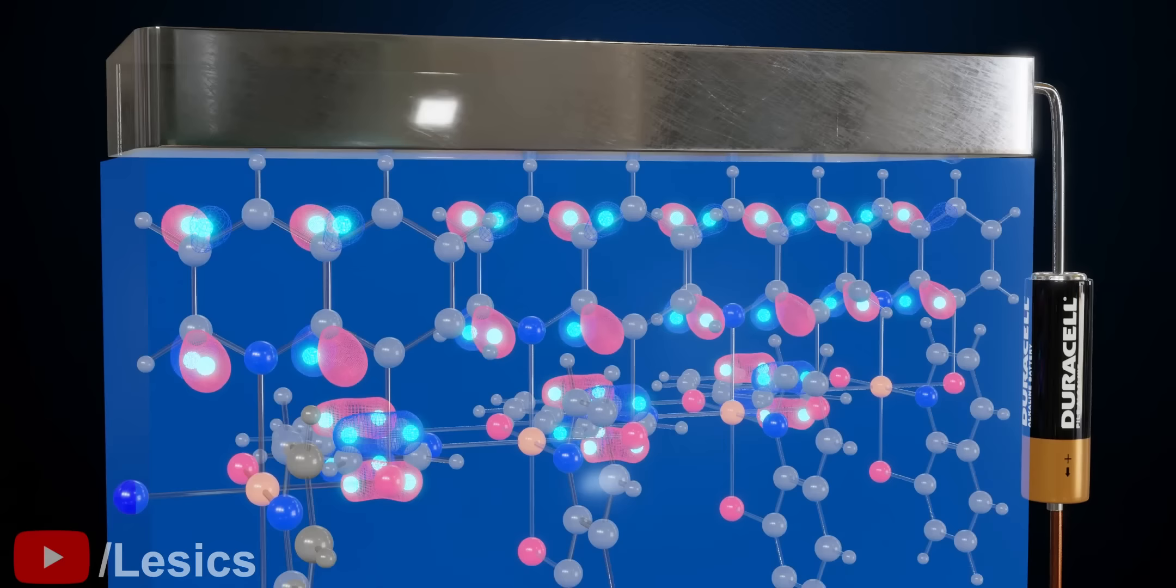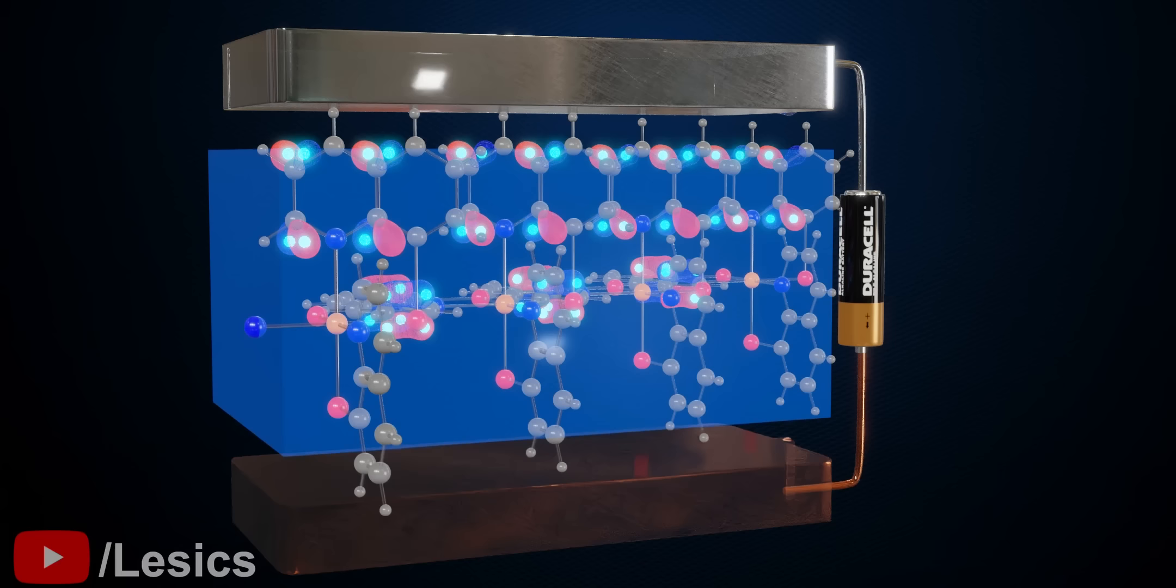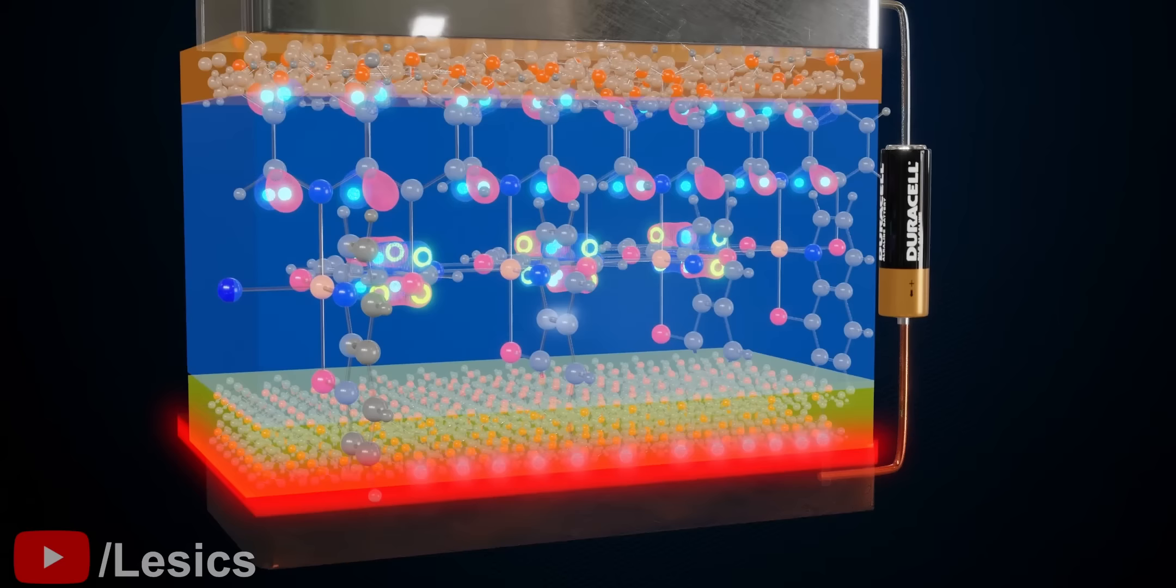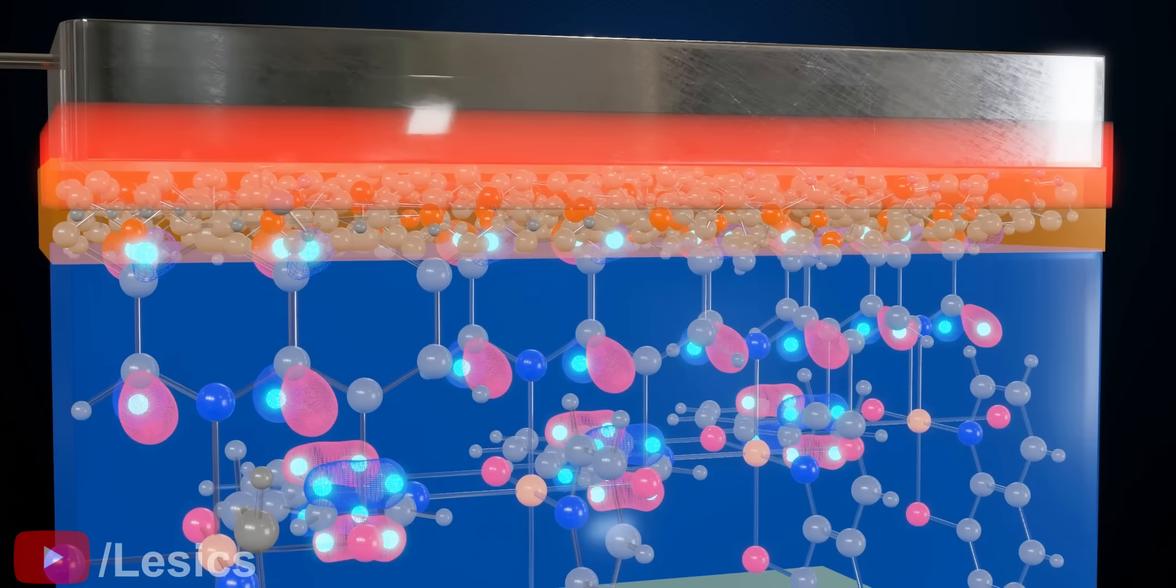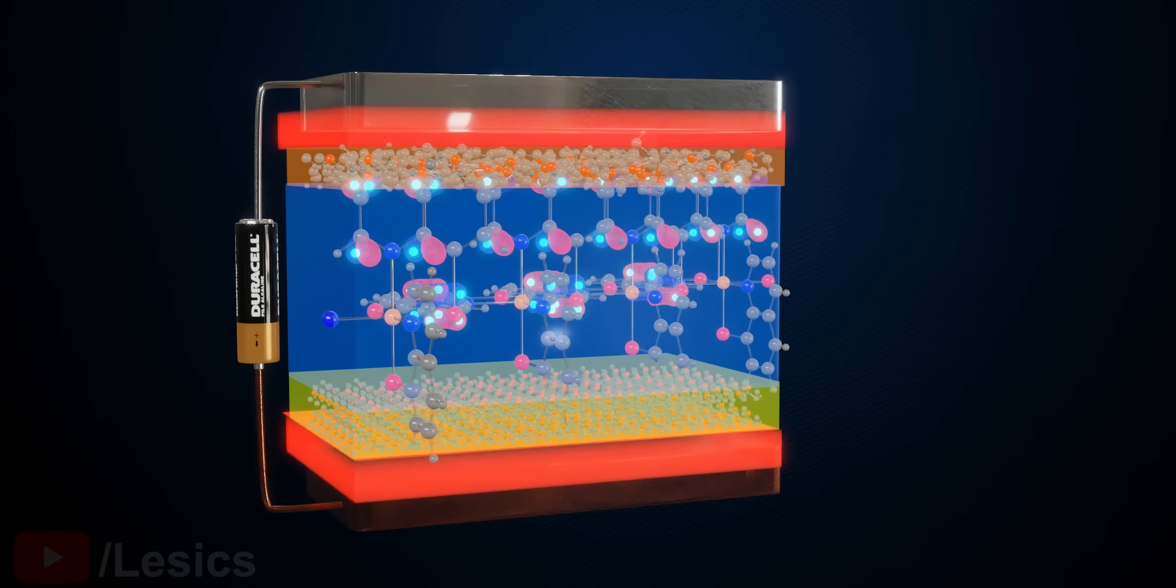This problem is solved by adding two different layers between the electrodes and the organic semiconductor. Due to the addition of those intermediate energy layers, the barrier will be reduced and electrons can be easily injected or extracted from the organic layers. However, here, charges have very low mobility due to hopping between the molecules. For this reason, we add more intermediate layers to further reduce the energy barrier and reduce power consumption.